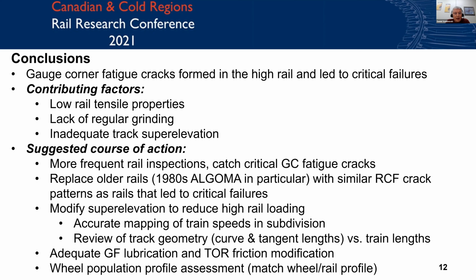This is a bit more problematic because you do need a very accurate mapping of the train speeds within that subdivision. Meaning that this analysis was done with the posted timetable speeds of the train speeds, which might not be the true train speed. So to get a clearer picture of how the trains are actually traveling through that zone, and then finding out which curves should have rails replaced first because they're at a higher risk of forming this type of derailment. That type of analysis would be beneficial to make sure that you don't get more derailments.